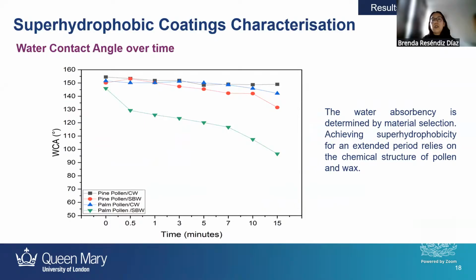So I did water contact angle over time. This will tell me how superhydrophobicity is maintained. I place a water droplet on top of the surface and leave it for up to 15 minutes, because the water droplet starts to evaporate. I can observe that pine pollen with Carnauba wax was more stable. It was superhydrophobic for almost 15 minutes, while the other samples start to decrease the contact angle, especially when I was using soybean wax. When using soybean wax, I can see a decrease in the contact angle almost immediately in some samples.